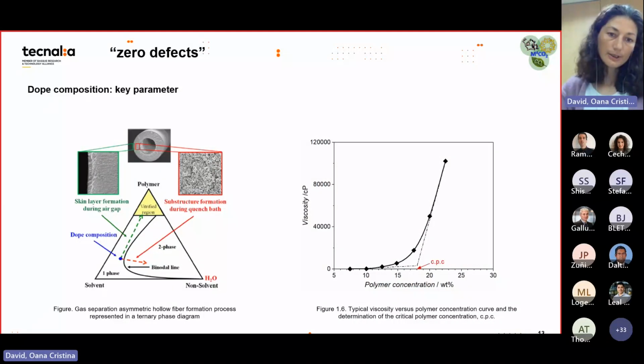Another analysis which we do is that we need sufficient viscosity for the thread to be self-sustained, so that the wet part of the fiber does not break during spinning when it comes out of the spinneret. For that, there is a minimum concentration we need, and we can determine it by making several solutions with different polymer concentrations inside the solvent. These are simpler solutions.